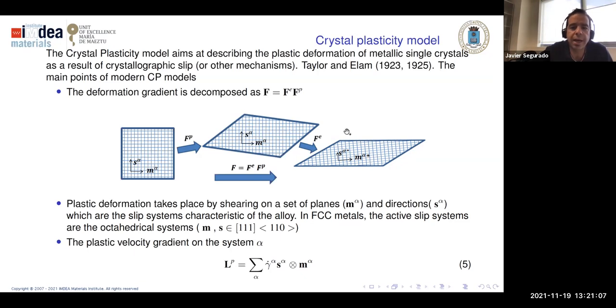And then we have a second or a final configuration in which we add the distortion of the lattice. The distortion is an elastic distortion. The atoms move from the equilibrium, so that's why you see this original lattice distorted. So the final configuration is this one, the only one that we see physically, but this decomposition is very useful because then we can model this part separately. What we say is that this part, that is only the pure plastic deformation, so it's a velocity rate, so the strain rate of this is just the sum of some shear rates, so some shear deformation in some planes and directions. Alpha are these planes and directions and are what we call the slip systems. So they are characteristic of the lattice we're using. In FCC, they are the octahedral systems. So alpha goes from 1 to 12 and are all these systems. Okay, so this is the kinematics.